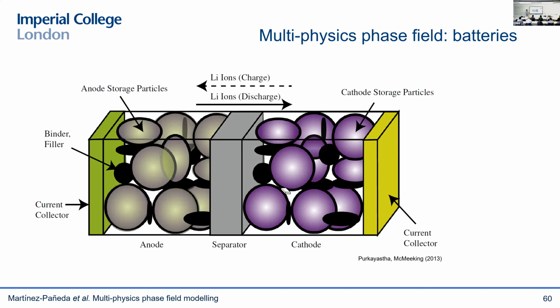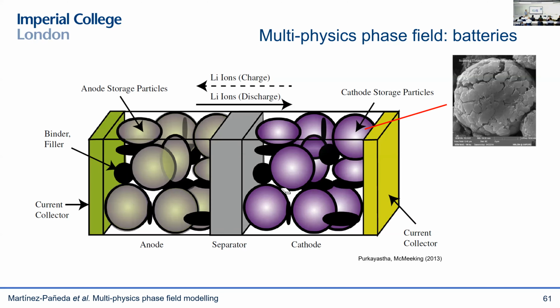And every time you have this, you have lithium intercalation within these storage particles, and this leads to some chemical strains and a swelling and shrinking of those particles. When you do that over multiple cycles, you get cracks appearing in those particles. Those cracks are arguably one of the main degradation mechanisms in lithium-ion batteries, so the reason why we need to change our laptops every couple of years.